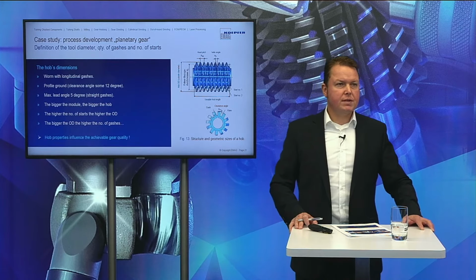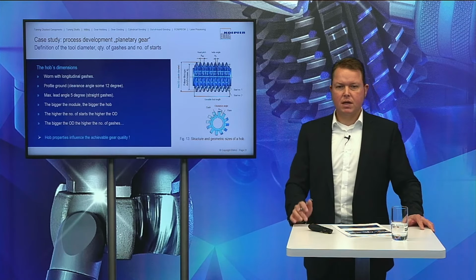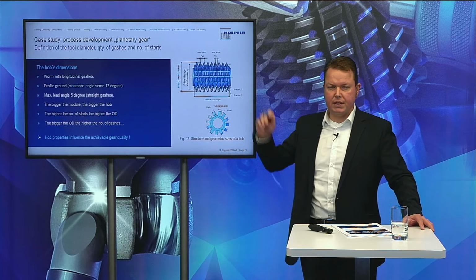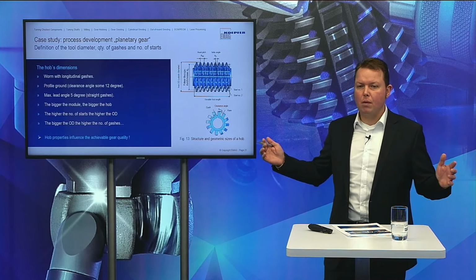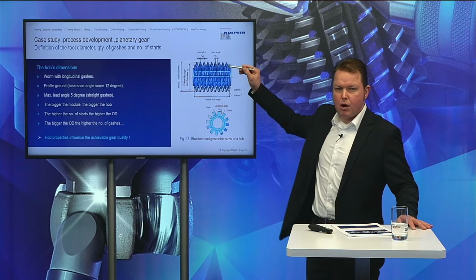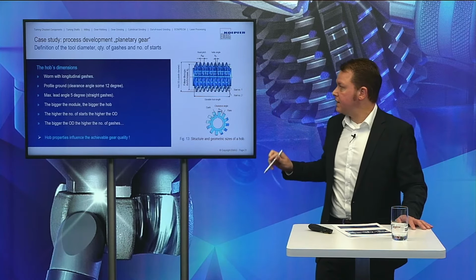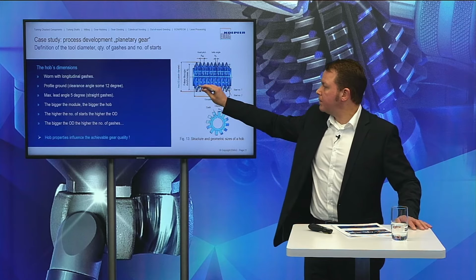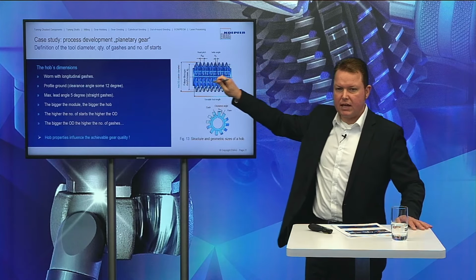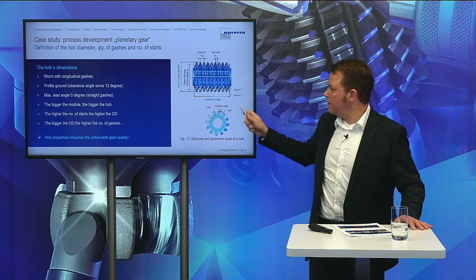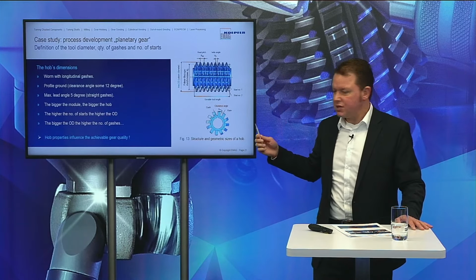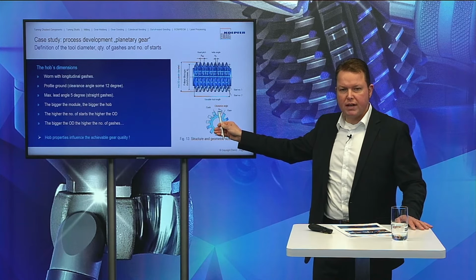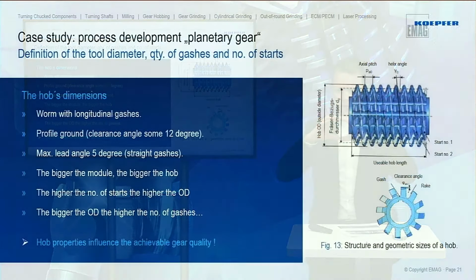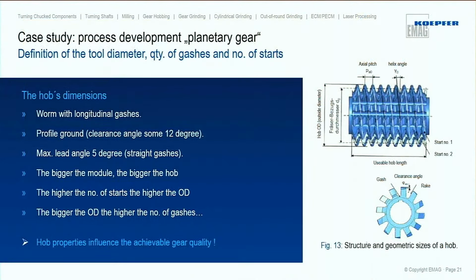The next issue is the definition of the hob dimensions. Here you can see in this slide how the hob actually is built. It is nothing else than a worm. A hob is nothing else than a worm. It has a helix, and it has gashes. So this helix is interrupted by axial gashes, and this creates the cutting edges. And in order to make sure it cuts, we will have a profile grinding disc with which we grind the individual teeth. So it is profile grinding.